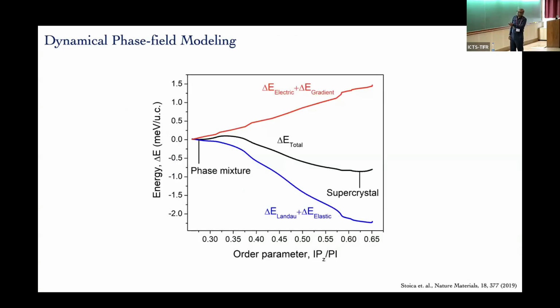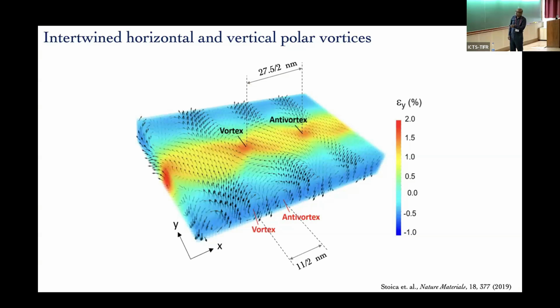Okay, so in terms of energy, what happens is you start with some mishmash here, and the total energy, you get the supercrystal here. It has lower energy than that. So light somehow could find a little barrier, get over this barrier, and find this local minimum, okay? And if you break this apart, you see that the Landau and elastic energy goes down. So it must be good because it must have gone down enough, although electrical energy and the interface energy, gradient energy goes up. Okay, so if you look more carefully, there are all these swirls left and right. So you can see these swirls we were already seeing left and right, left and right. But now there are swirls up and down. So it's almost like DNA origami. You've got some swirls like this, you got some swirls like this that were not there before, but light has created these things.